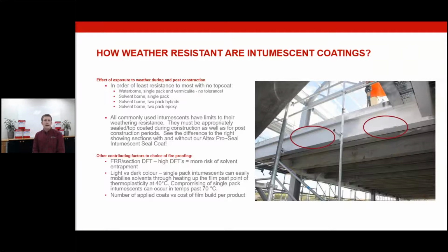You've also got the number of coats applied versus the cost of film build per product. With a lot of the 2-pack hybrids and epoxies, you can apply much higher film builds in one application compared with the single packs. Single packs, you're limited to 800 to 1,000 microns per day. Most of your 2-pack hybrids and epoxies, you can get 3, 4, 5,000 microns applied in one coat. It's quite easily done depending on each individual product. So you can get some project efficiencies, and critical timelines being impacted there, depending on the type of intumescent that you choose.